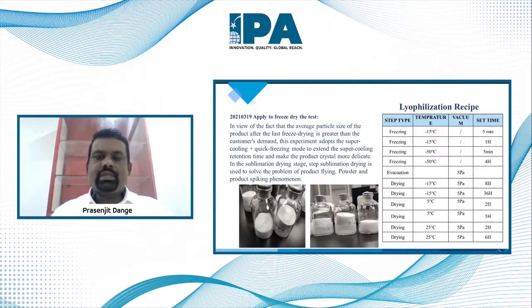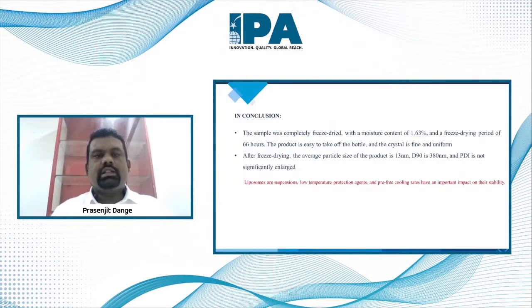With this particular cycle applied, we got the results as shown on the left side in the picture. And the conclusion we can take from this, next slide please. The sample was completely freeze-dried, with a moisture content of 1.63%, and the freeze drying period was 66 hours. The product is easy to take off the bottles, and the crystal is fine and uniform.